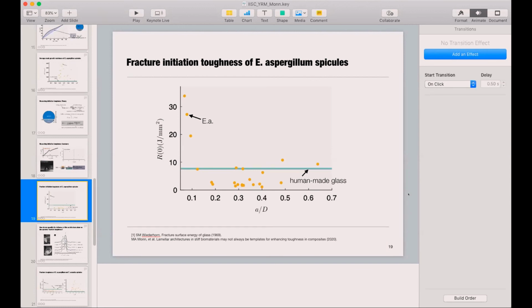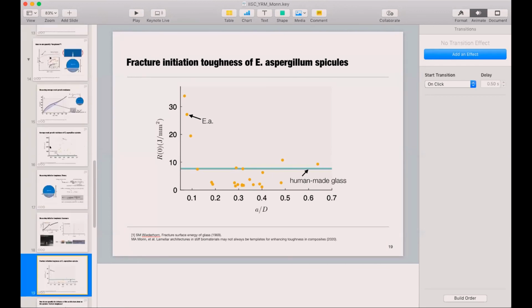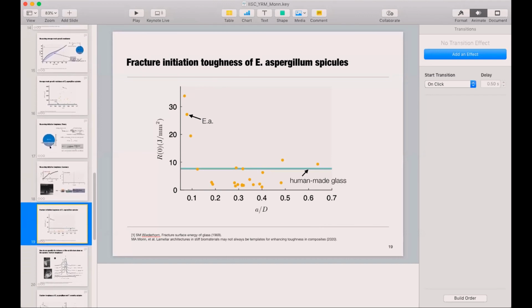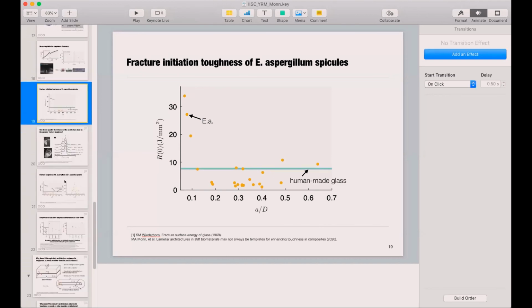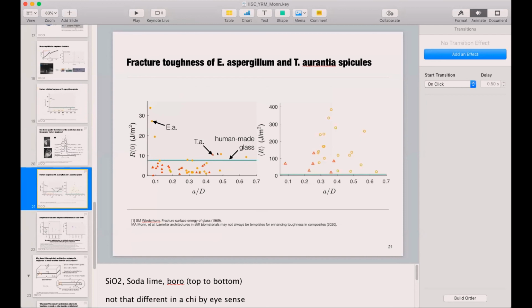Yeah, if I may just continue with that question. The reason I asked this is even in monolithic materials, we are seeing that for very short cracks, there is sort of a spike in the fracture toughness compared to the longer ones. Yes. So I was not sure whether it's the effect of the architecture in the material or whether it's something to do with short cracks versus long cracks. So I think in this case, it is the effect of the architecture. You can see that in this plot on the left, where we have similar crack lengths in terms of a by D for the monolithic reference, the TA, Tethya aurantia, and you don't see that same increase.